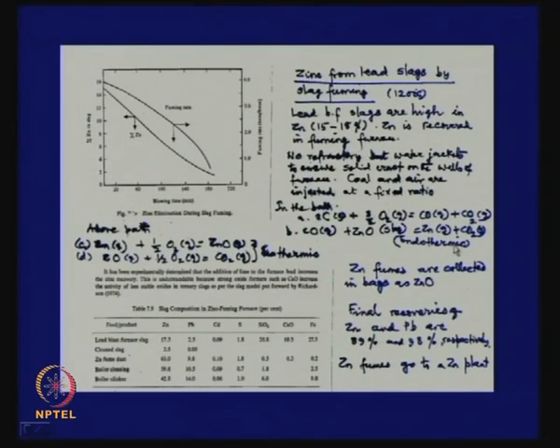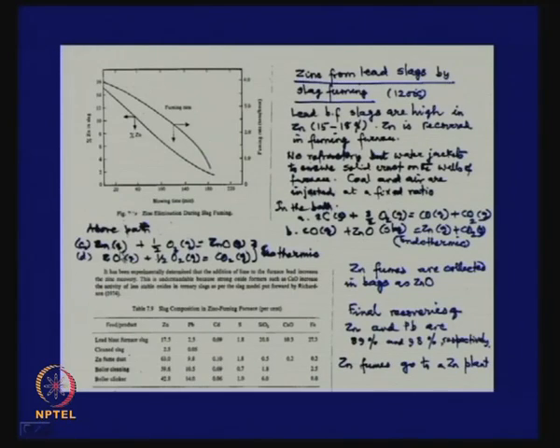So, it tends to cool the entire bath. The heat can be compensated like this. Above the bath, when zinc vapors come out, they react with the oxygen in the atmosphere and form ZnO fumes, which is exothermic. Also, the CO that is coming out will form CO2 as it comes out, or it can be combusted to form CO2, that is also exothermic, that will give heat to the bath. So, some heat is gained by oxidation of zinc and oxidation of CO. This is the fuming process by which you are recovering zinc from the slag essentially as zinc oxide fumes.